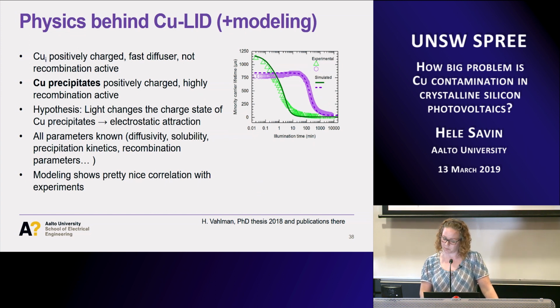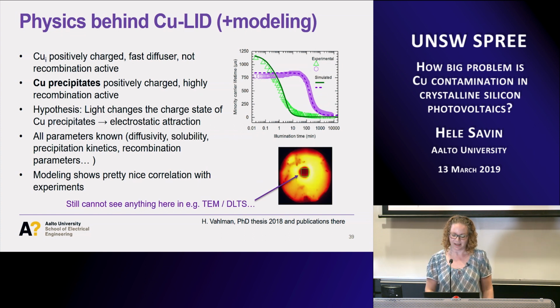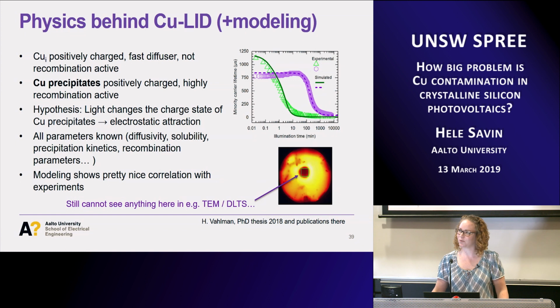What is still quite annoying to me is that if we have these copper precipitates, why I don't find them with any methods. You don't believe how many hours I have spent in TEM looking for these tiny precipitates, or in DLTS. I mean, we have a millisecond lifetime and spots where the lifetime is microseconds. Why do I still not see any actual defects other than in lifetime? So it's really something I don't like. On the other hand, if we look at the modeling results, which will actually show us the precipitate size distribution, they are actually very small precipitates, and the density is relatively small.